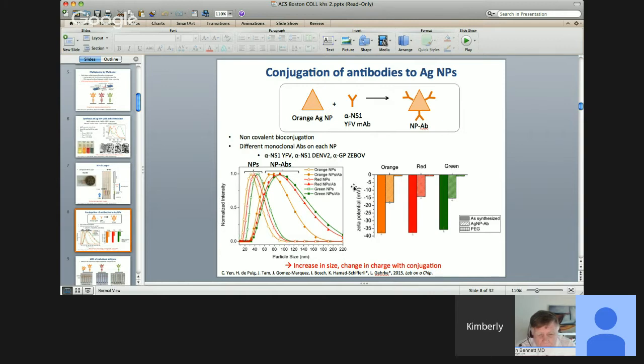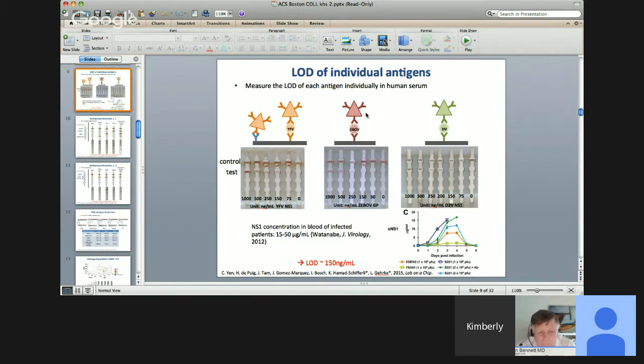And pretty much from there, we just verify that those antibodies are on the surface of the particle using techniques such as DLS and zeta potential measurements. Basically, we look for a change in the size and the charge of the species. Okay. So then what we do is we make sure that each of these individual nanoparticle antibody conjugates can detect the antigen individually in human serum.